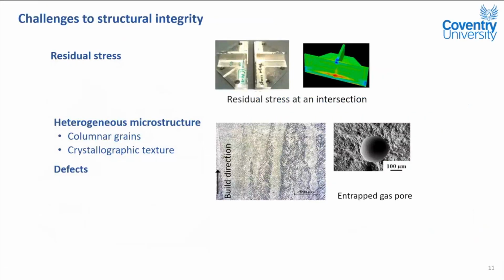So the challenges to structural integrity when using additively manufactured structural materials, people often say, are three. One is residual stress, which is already there and often in tension, the red, balanced by the blue in compression far away. Usually the tensile stress is at the geometry change. So people obviously think this is an issue. The second is heterogeneous microstructure, typically presented by columnar grains during additive manufacturing. The vertical direction is the material build direction. There is also very strong crystallographic texture.